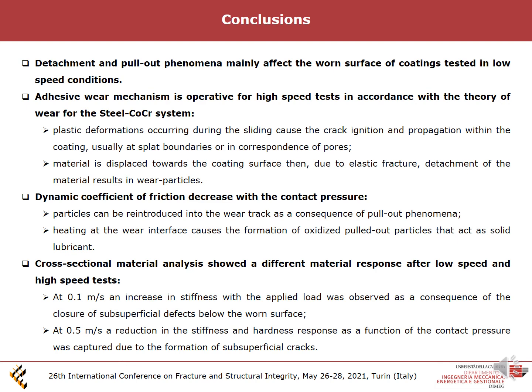Concluding, cross-sectional material analysis showed a different material response after low and high-speed tests. In fact, at 0.1 meter per second, an increase in stiffness with the applied load was observed as a consequence of the closure of subsuperficial defects below the worn surface. On the other hand, at 0.5 meter per second, a reduction in the stiffness and hardness response as a function of the contact pressure was captured due to the formation of subsuperficial cracks inside the coatings.